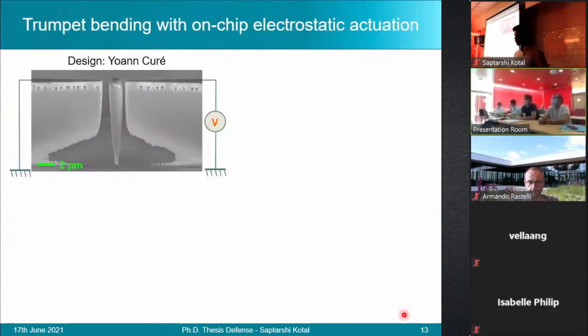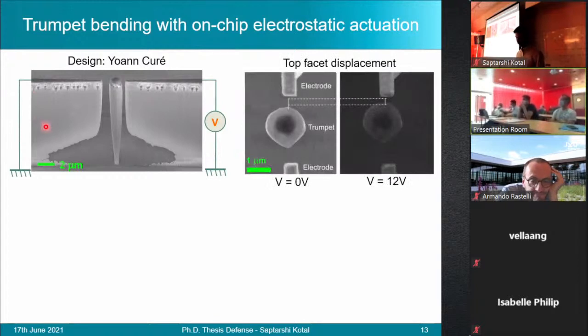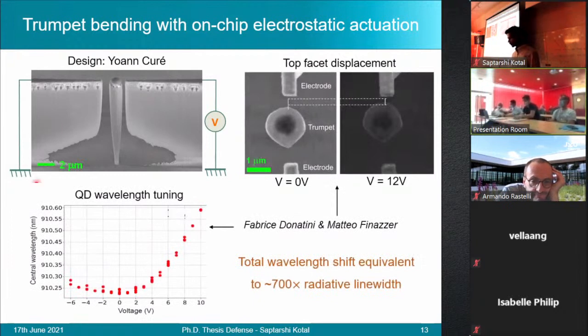In the course of my PhD, I helped to design and fabricate such an integrated device where we introduced 2 electrodes on either side of the photonic trumpet. Then, by applying a potential difference across the 2 electrodes, we were able to displace the top facet of the trumpet. And by applying different potential differences, we could shift the emission wavelength by a maximum of 0.37 nanometers. What we see here is the graph as a function of applied voltage and the corresponding wavelength shift. Now, these measurements were carried out by Fabrice Donatini and Matteo Finazzer, and these 0.37 nanometers of optical shift is equivalent to roughly 700 times the radiative line width of a quantum dot in these systems.